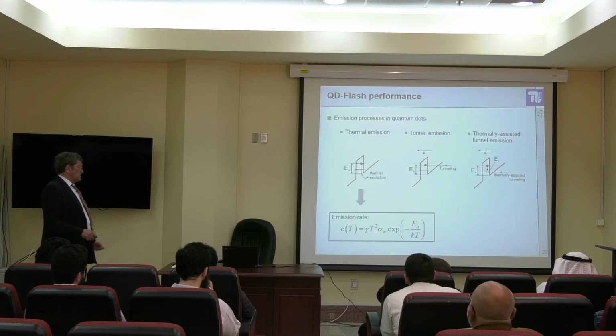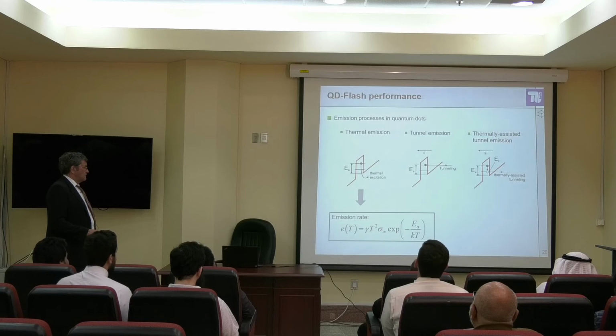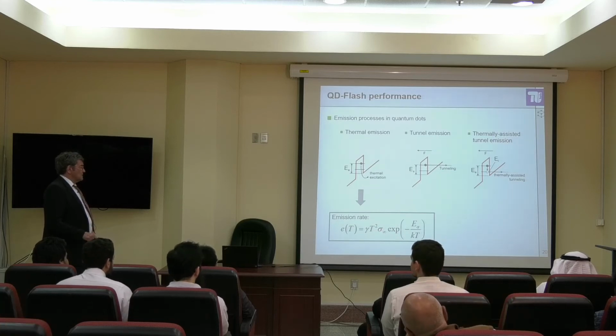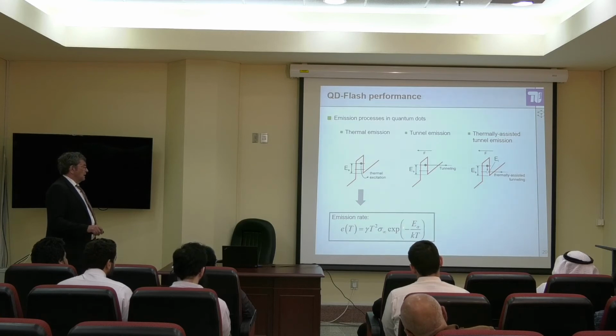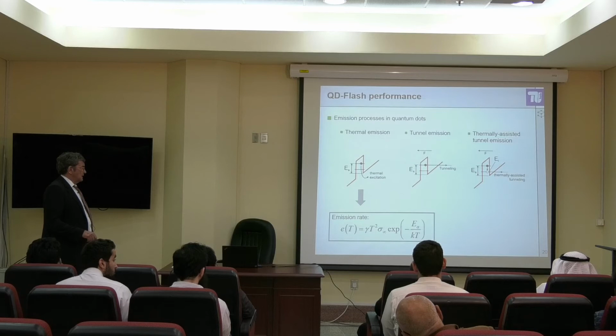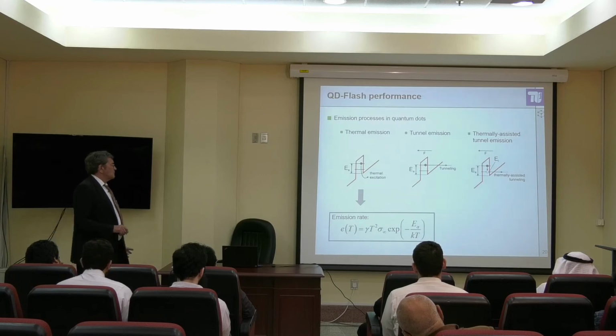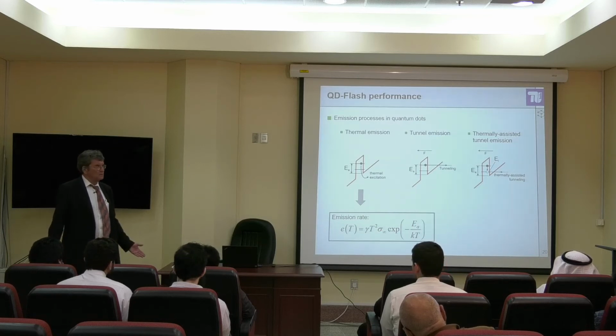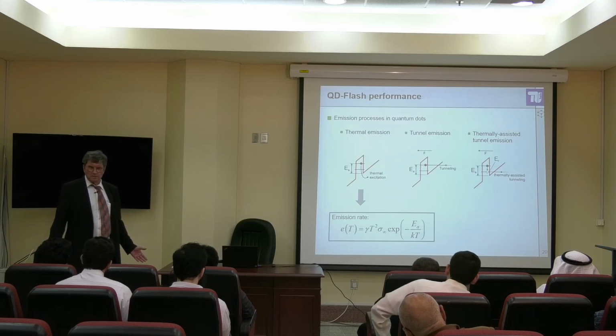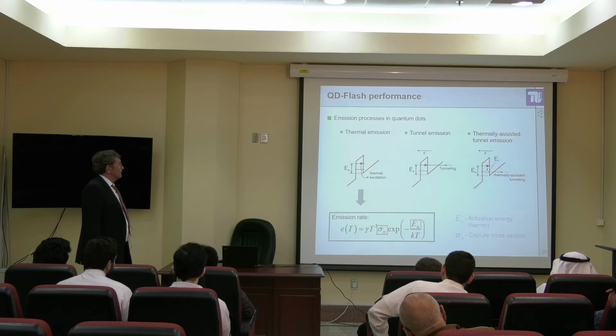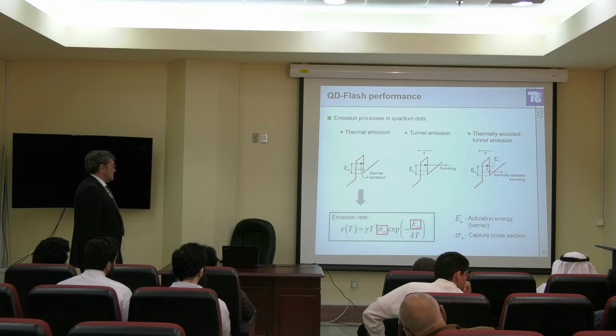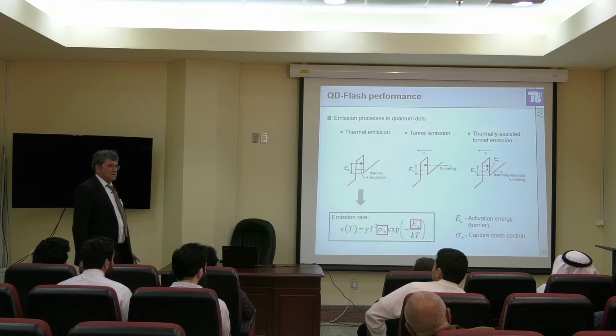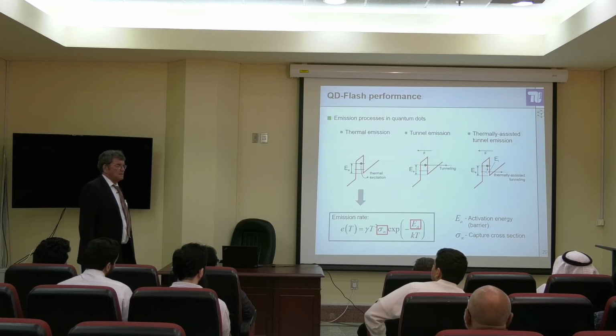Emission rate depends on the square of the temperature and the so-called capture cross-section, and exponentially on the activation energy E_A. So it's a linear dependence here, but an exponential dependence here. And apart from temperature, it's very fortunate that you have only two parameters to think about and modify. Only two. It's comparatively easy, easier than, for example, the cutoff frequency of a laser. So, activation energy and capture cross-section. What's gamma? It's a constant, you can calculate it.